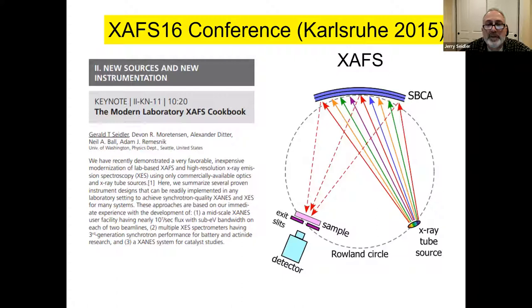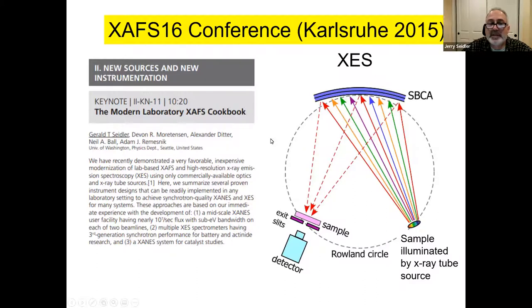So what we showed in that 2015 talk was that we could take the spherically bent crystal analyzers that had been developed over several decades for synchrotron emission spectroscopy and especially for RIXS, and we could use those in the laboratory in a Rowland circle geometry. So you would have your X-ray tube source, which is very polychromatic, and use the spherical analyzer in this geometry to make a monochromatic beam, and then scan symmetrically the position of source and detector to make a scanning spherical monochromator. Or for emission spectroscopy, now your multicolored X-ray source is a sample illuminated by an X-ray tube, and otherwise the instrument works exactly the same.